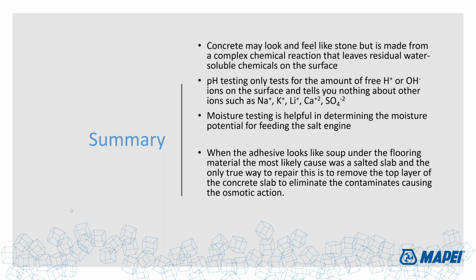Well, it's going to be the unreacted Portland cement base that's still in the concrete. It's going to continue to pull some moisture out of the slab and continue to hydrate. That's why concrete gets stronger and stronger over time as it continues to pull moisture out of the concrete slab. But there's only a limit to how much moisture the Portland cement can actually pull out of it.